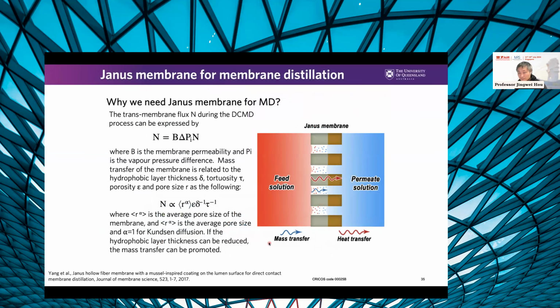That's one example. The other example, probably not really related to the MOF, but quite an important topic for the membrane. Sometimes we have a process called membrane distillation. In membrane distillation, we want the membrane to be thick, because the driving force is the temperature difference across the membrane. So we want a thick membrane, so it can keep the temperature difference larger. But we also want a thinner membrane, so it reduces the mass transfer resistance, right? So that's pretty intuitive. But the real question is how I can make a membrane thick and thin at the same time. That may sound totally impossible, but in reality, we can achieve that by using a Janus membrane.